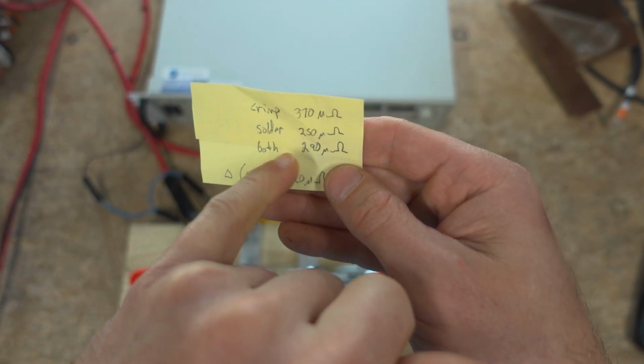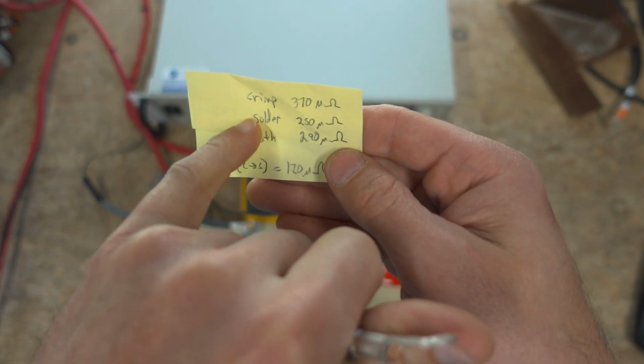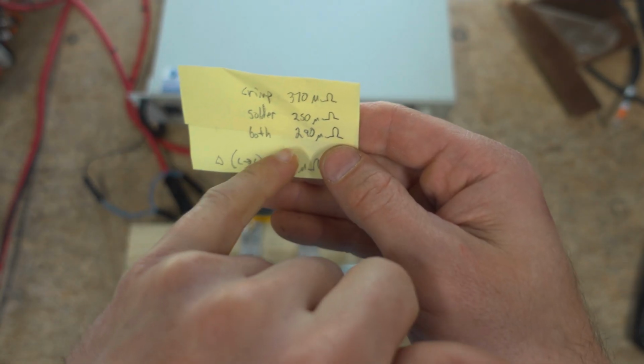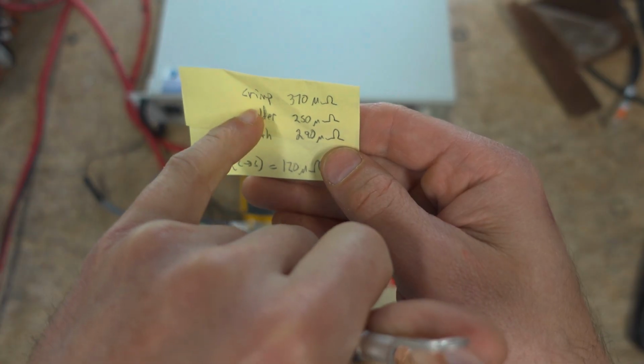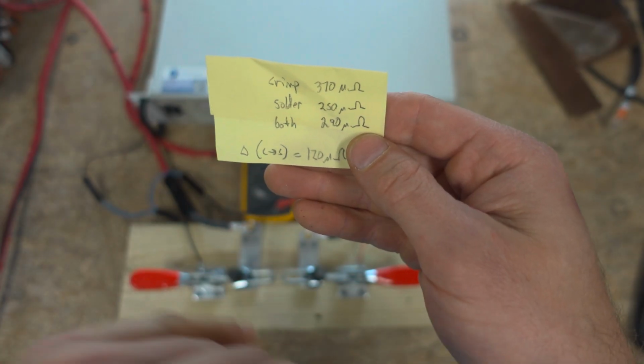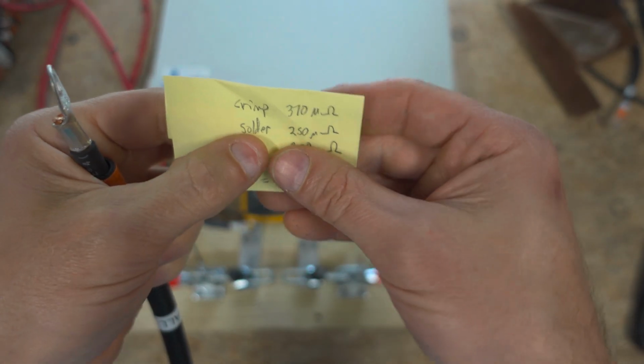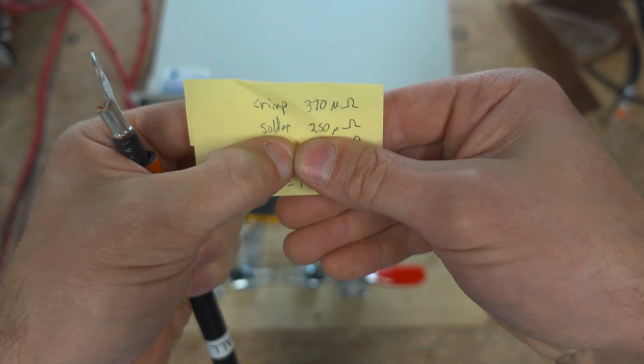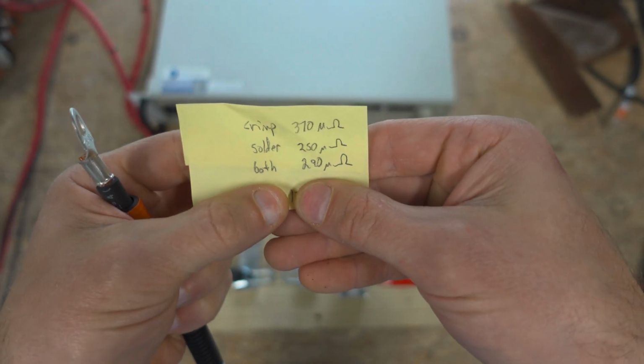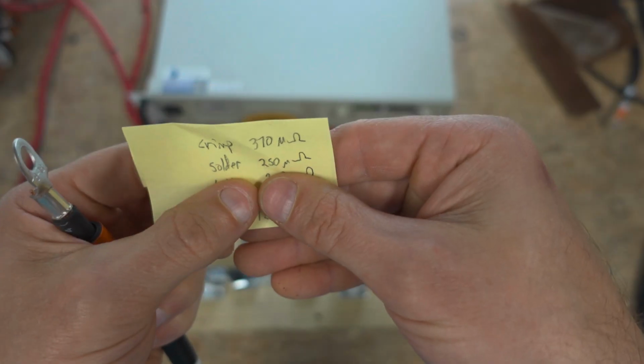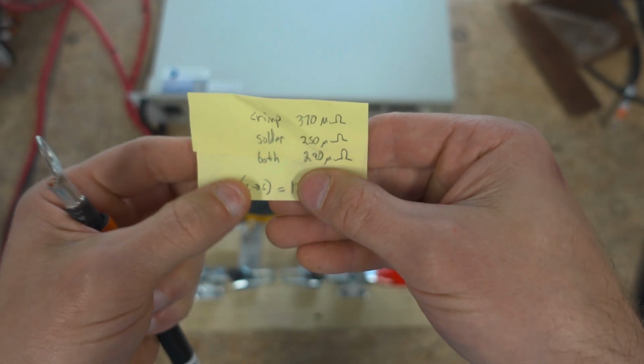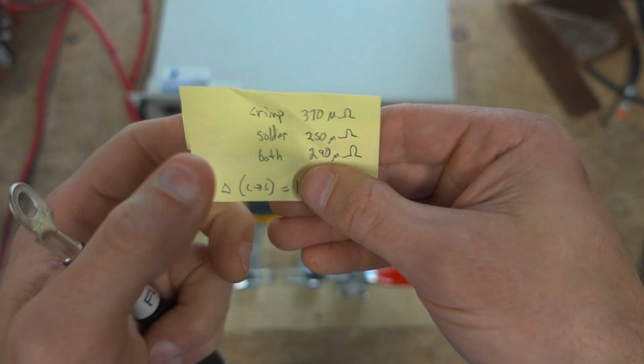It's weird to me that if solder was better, that doing both would be worse. It seemed like maybe the soldering method was done differently. I don't really have any comment on that. I'm mainly looking at the difference between the crimp and the solder. Because no one's going to do both. It's kind of weird. Unless you're soldering it after the fact because the crimp is bad.